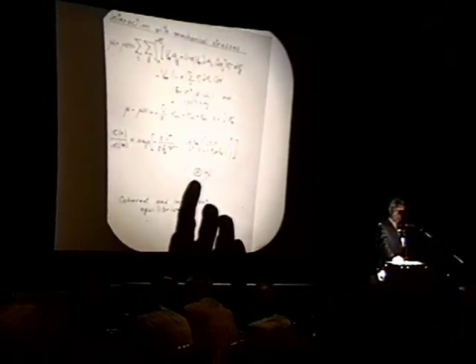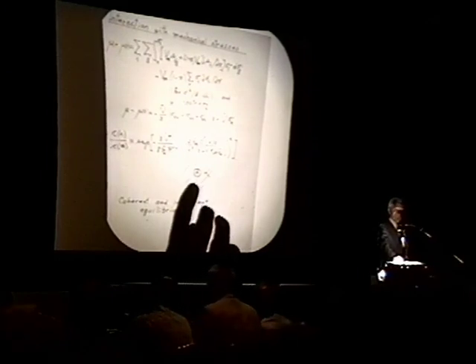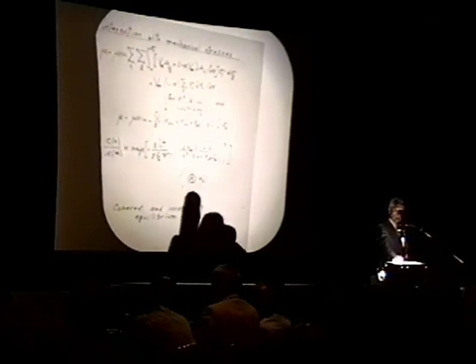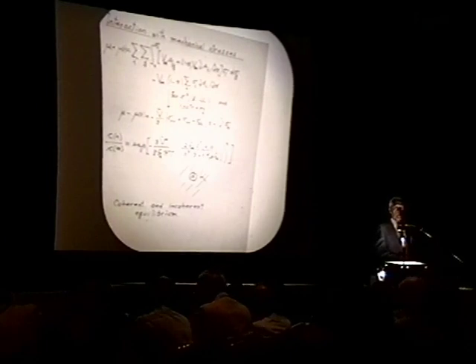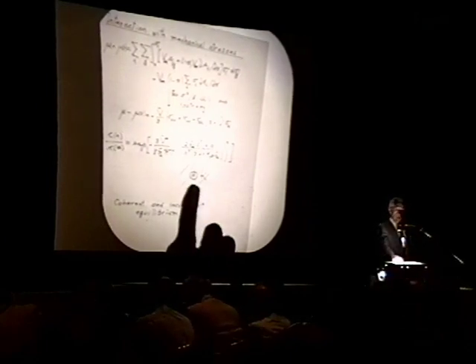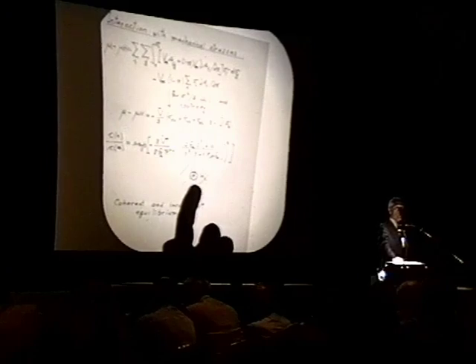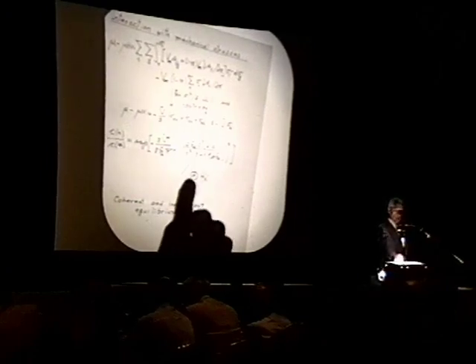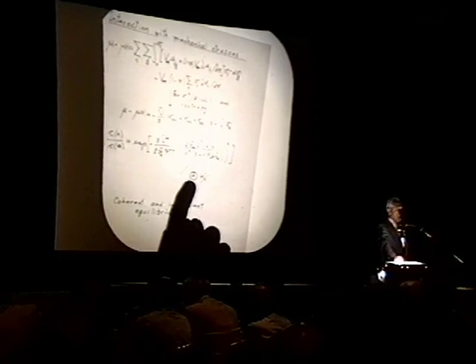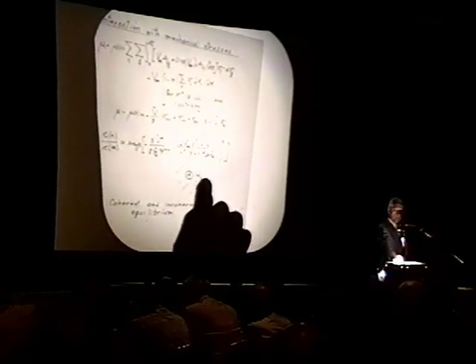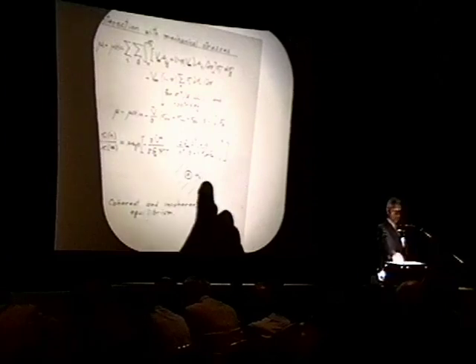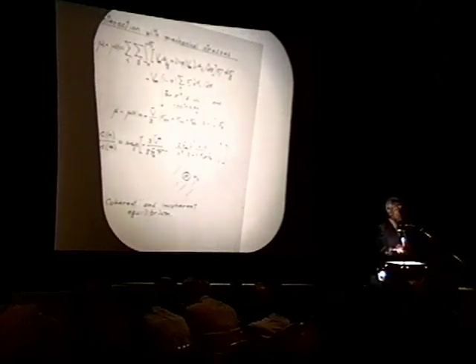Suppose you have grown a beta phase palladium, for example, inside of the alpha phase. By virtue of the fact that the palladium atom is effectively immobile compared to the mobility of the dissolved species hydrogen, the beta phase will initially grow in such a way that only hydrogens will accumulate at the higher concentration in beta, leaving the lattice lines between the alpha phase and the beta phase effectively continuous. We call that a coherent precipitation or coherent growth.